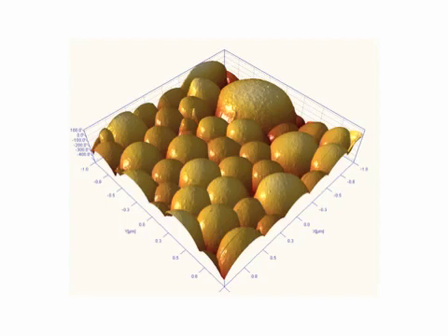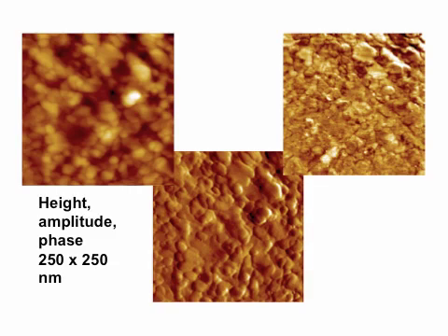So here you see an AFM picture of a film that has been made from these types of materials, and you'll see that the surface looks a bit bumpy. In the previous picture, I showed you that these clay discs were Laponite clay discs. They're a disc size of 25 nanometer by 1. So now the question is, are they really discs, and what do they look like? There's one large particle here, so we zoomed in on top of the surface of the large one and checked whether we could see any discs lying on the surface.